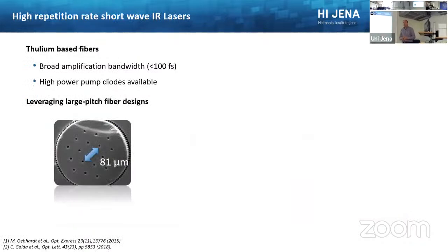One material that you can use is thulium, as I've shown you already on the first slide. The nice thing about thulium is it has a broad amplification bandwidth. You can build systems that output less than 100 femtoseconds of pulse duration. You have high power laser diodes, normally at 793 nanometers, quite widely available. And you can now combine this material with the technology we have developed before. For example, this is a picture of a thulium large pitch fiber. It's the same basic design, just your core is doped here with thulium. And you can see you can go to quite large diameters also due to the larger wavelengths of thulium.